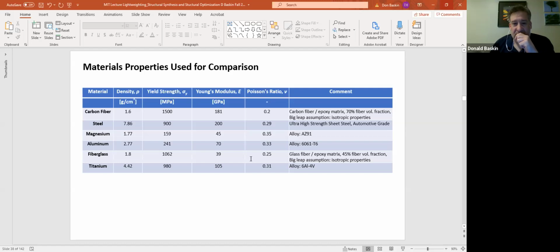Magnesium has the lowest density, I think, of any structural material, even more than beryllium, at 1.77 grams per centimeter cubed. The yield strength is on the low side. It's only 159 megapascals, or 0.159 gigapascals. And the Young's modulus is also very low at 45 gigapascals. For aluminum, the data shown here is for a very common aluminum, 6061-T6. Talked about that in the previous lecture on how to heat treat 6061-T6. The density is 2.77. The strength is still pretty low at 241 megapascals. The Young's modulus is still very small compared to steel, 70 gigapascals.